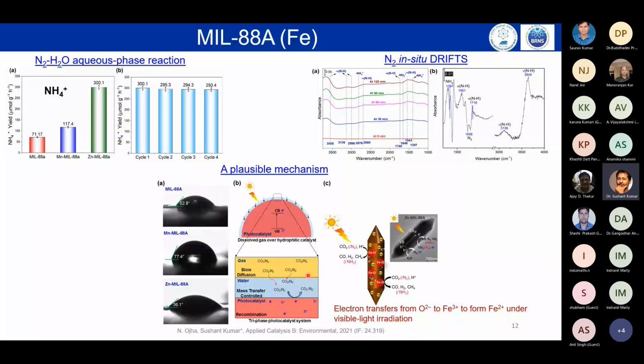Now, in another work, a follow-up to this work, with the help of one of our colleagues, we performed some molecular dynamics simulation, and what we have seen is that when we have a hydrophilic surface, the CO2 molecules do not penetrate easily, and they also do not stay for long. And when we have a hydrophobic surface like the one we are seeing here, manganese, it penetrates well and stays there for a longer time, and that helps in the photo conversion of the CO2. Now when we compare manganese and zinc, as I told you, zinc was performing better than manganese, so how could this happen?